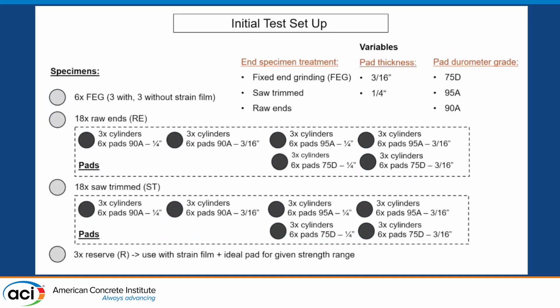What I'd like to note is that for each end condition, pad thickness, and hardness, we tested about 3 cylinders initially. For example, raw end 90A and 1/4, or a saw trim 75D and 3/16. And we left 3 reserves to see what the ideal condition was, or which end condition matched the fixed and ground state. And we could compile more data points for the ideal condition in that test.